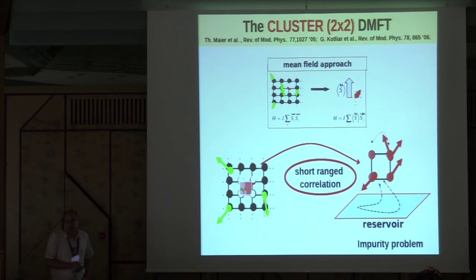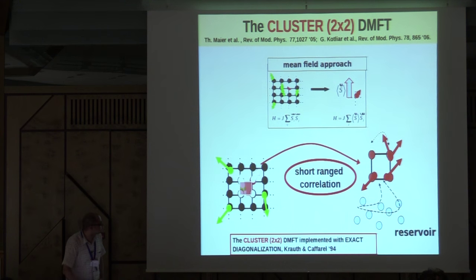You have already seen many talks about dynamical mean field theory. The cluster extension of dynamical mean field theory is in spirit the same theory, but the quantum many-body problem on the lattice is replaced by an impurity, a cluster. So you don't have just a site, you have a cluster of sites, and this cluster of sites is embedded in a bath of non-interacting electrons, which mimics the rest of the lattice. And then there is a self-consistency condition that relates this effective cluster impurity model to the original lattice problem, like in classical DMFT. I will not enter the details about that, just to tell you that the difficult part is to solve this impurity problem, like in DMFT.